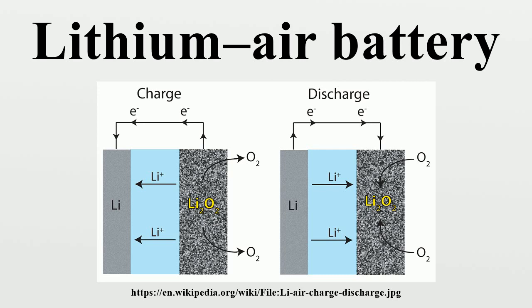Upon charging and discharging in aprotic cells, layers of lithium salts precipitate onto the anode, eventually covering it and creating a barrier between the lithium and electrolyte. This barrier initially prevents corrosion, but eventually inhibits the reaction kinetics between the anode and the electrolyte. This chemical change of the solid electrolyte interface results in varying chemical composition across the surface, causing the current to vary from point to point. The uneven current distribution furthers branching dendrite growth and typically leads to a short circuit between the anode and cathode. In aqueous cells, problems at the SEI stem from the high reactivity of lithium metal with water.